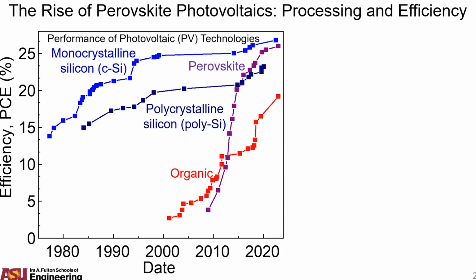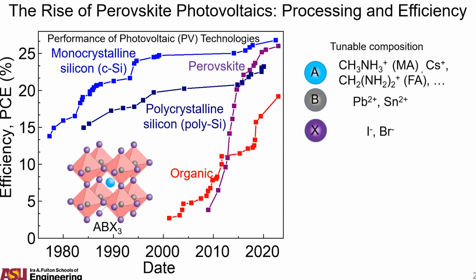But first, the promise and the opportunity. When compared to other, at least terrestrial technologies, perovskites have really done remarkably well. This is showing AM 1.5G spec efficiencies up to 26% now, and AM0 is exceeding about 23.5% or so as single junctions. The amazing part about perovskites is that they can be tuned fully. This describes a crystal structure, so you can tune the band gaps and create tandems and multi-junctions out of perovskites by changing the composition of the lattice.